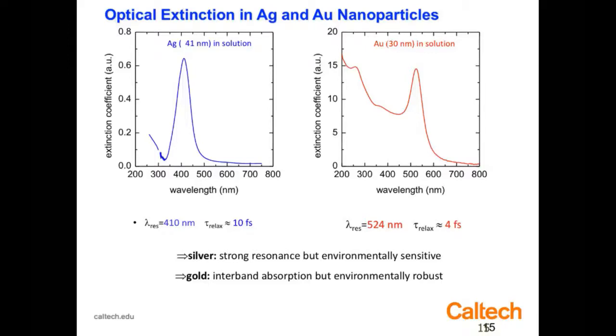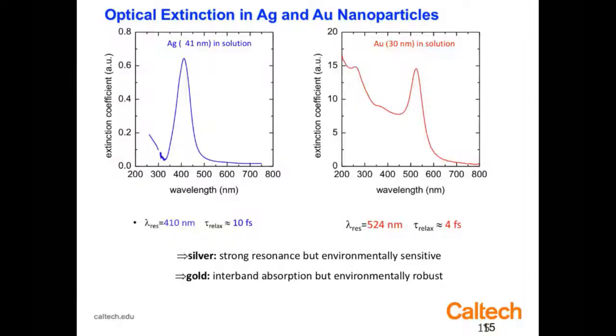Similarly for copper. Silver is a sort of colorless metal, and the reason is because its plasmon resonance lies very close to the blue, so it's a little bit bluish. People talk about a blue complexion. If you swallow a lot of silver nanoparticles, your face will turn blue due to this blue light scattering. The characteristic line width here is due to the dephasing or relaxation time of the plasmon decay time. It's relatively broad as these things go, and the decay times for plasmons are relatively short.